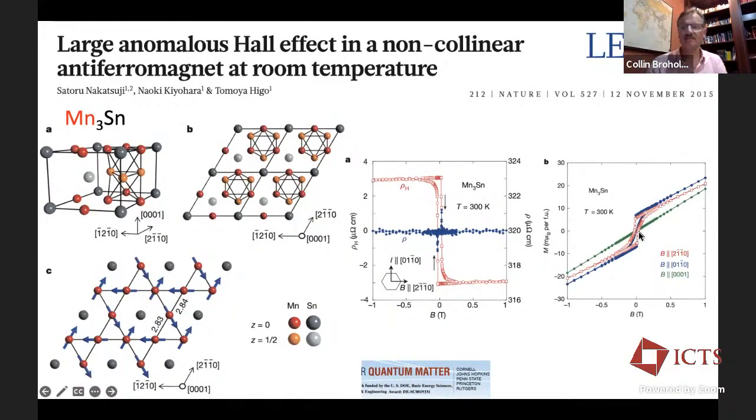So really, really small magnetization is consistently present, and is, in a sense, the reason that one is able to manipulate the magnetic order by the application of a magnetic field. So all of this takes place at room temperature in a compound of fairly earth-abundant elements that are not particularly poisonous. So it has a real possibility of an application that would involve the Kagome lattice.